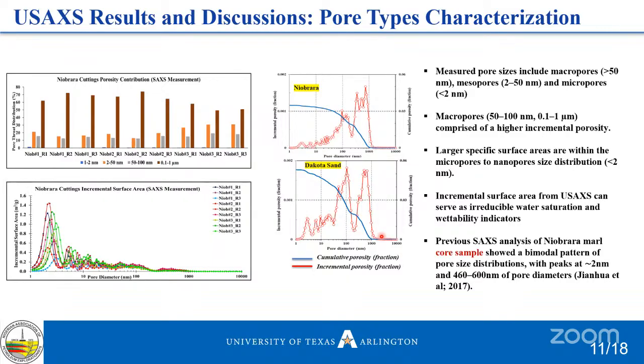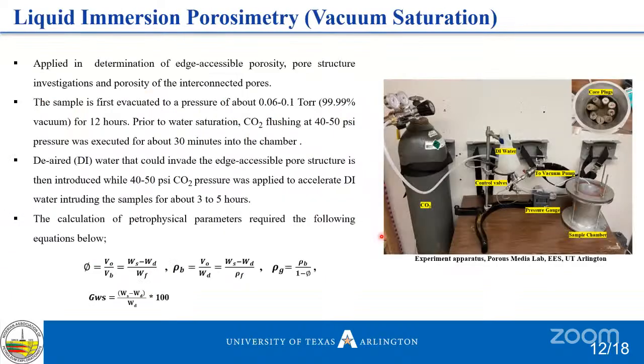It could be related to non-characterization of micropore porosities, because an increment of porosity in the range of 0.1 to 2% can make a big difference in terms of porosity cutoff. If you use a pay cutoff of maybe 10%, and you don't include the micropore porosity, which might be 2%, you may end up cutting off an 8% porosity interval, which cumulatively is 10%. And that is very, very crucial when it comes to low pay reservoirs.